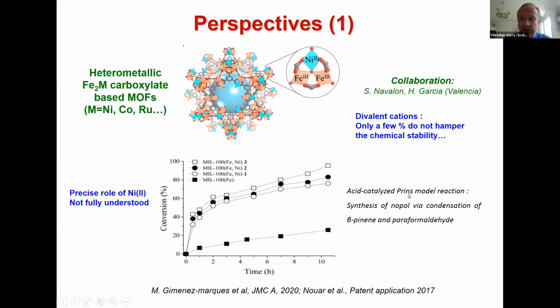They looked at the acid-catalyzed Prins model reaction. Basically, you have a condensation of pinene and formaldehyde to form nopol. Here this is the pure iron(III) MOF, and this is the doped nickel iron MOF. And you see that you have a very strong increase of the activity. We tried to understand the precise role of nickel. It is not documented for this reaction, and it is not fully understood. So we are lacking understanding here, but it shows that by just changing a little bit, by doping, we could keep the chemical stability and modify strongly the catalytic activity, and maybe for the DeNOx reaction.